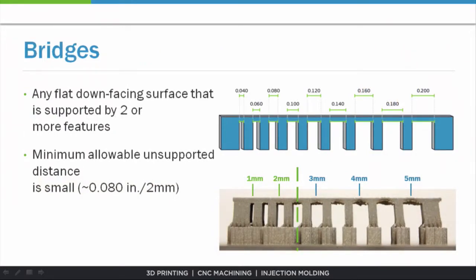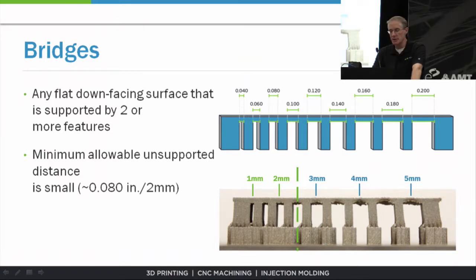Bridges is the next thing we're going to talk about. So if you look at, obviously a bridge, any flat down-facing surface that's supported by 2 or more features, right? As you look at this, we've designed it in with larger and larger width within the bridge. And the stresses here create some of the challenges. So the minimum allowable distance of an unsupported bridge is about 2 millimeters. Again, you can see in the lower left is the part actually built. At 1 millimeter and 2 millimeter, you're okay. Once the span starts getting above that into 3, 4, and 5 millimeter, again, you've got an unsupported down-facing surface that's too far. The stresses involved cause it to fail.